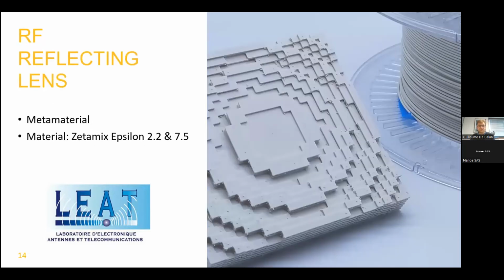Another example here of a reflecting lens. So it's not a lens this time. It's actually a reflector and a lens at the same time. The electromagnetic wave will come in from the front and then come out from the front also. Even though the material is only a dielectric, because of the way it is structured below the wavelength, the wave is actually going to be reflected. Here we use two materials in this print. We've used Zetamix Epsilon 2.2 and 7.5 because you needed strong differences between the permittivity of certain zones. You needed high permittivity and relatively low permittivity.